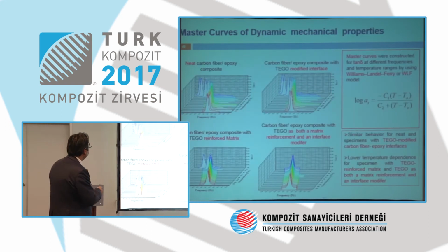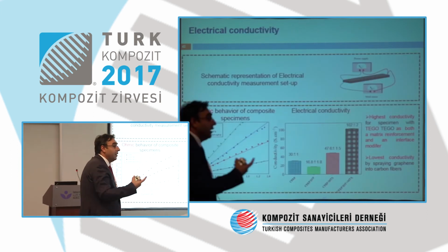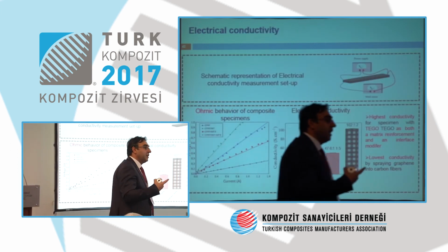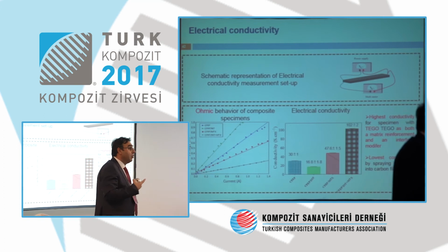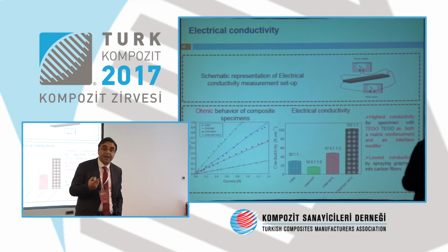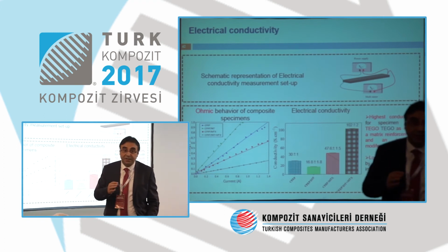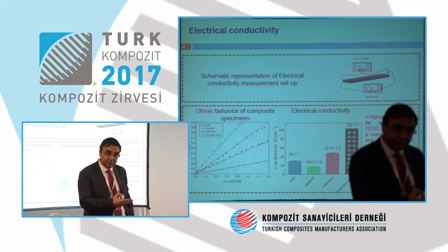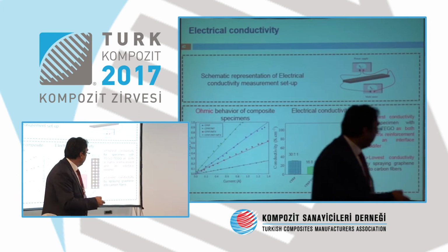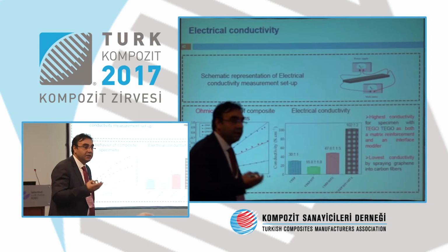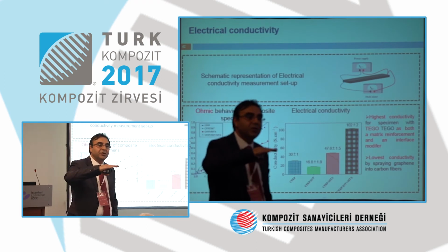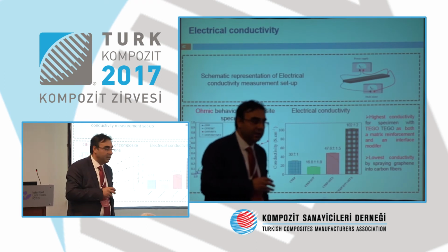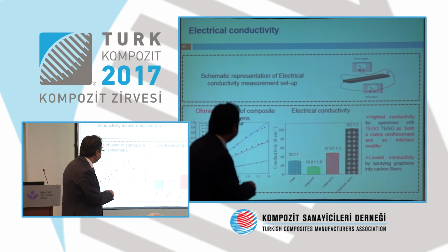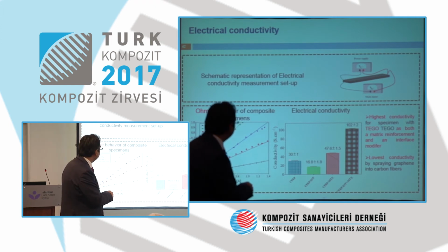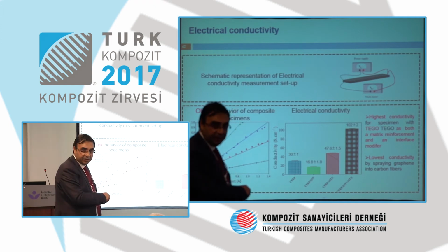I'll just skip this part. We also look at not only the mechanical properties, but also the electrical properties. The graphene, if it is not defective, is highly conductive. Carbon fiber is conductive. And we look at the in-plane conductivity of our material. This is your neat material. It is around 30 Siemens per centimeter.